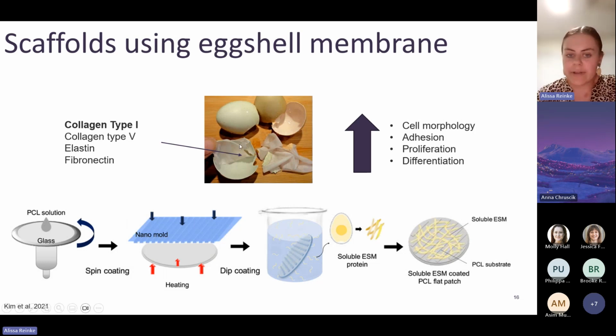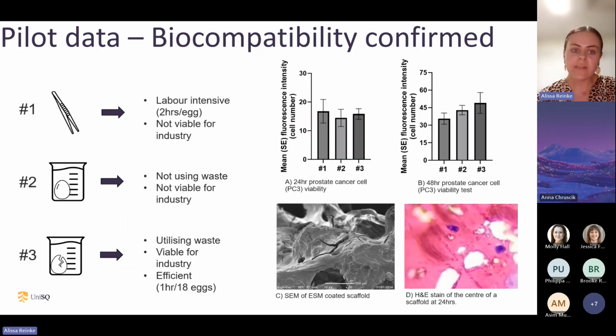After I created that solution, I literally just put the scaffolds in there for about 2 hours, took them out, and then put them into the media with the cells, and allowed the cells to start growing. Now, the initial way that I was creating the eggshell membrane protein was very, very labor intensive. It involved using forceps to peel away the membrane from the eggshell. It took about 2 hours for every individual egg, and this is just not viable for industry.